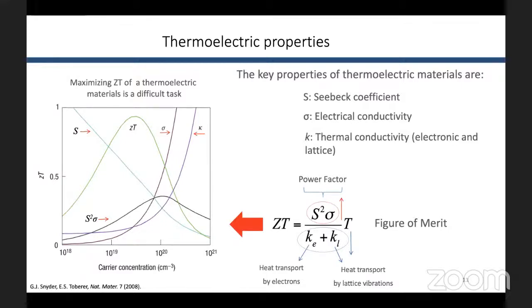And to find a material with interesting properties to become a thermoelectric, you need a better combination of these properties. And this is a difficult task. As you see in the figure, the better combination is hard, because, for example, if you work with a carrier concentration between 10 to the 18 and 10 to the 21, when carrier concentration increases, for example, the Seebeck coefficient decreases, and in parallel electrical conductivity increases and electronic thermal conductivity increases too. And in the majority of cases, engineers are working separately.